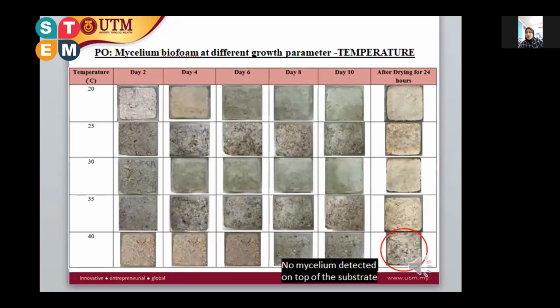So next, these are the following figures that I want to show of the growth of PO at the different factors studied, up to 10 days after the drying process. This figure shows the appearance of the biofoam at different temperatures, and we can see that at a temperature of 40, after re-drying for 24 hours, there is no mycelium detected on top of the substrates, which means that at a temperature of 40, PO cannot grow further after drying for 24 hours.